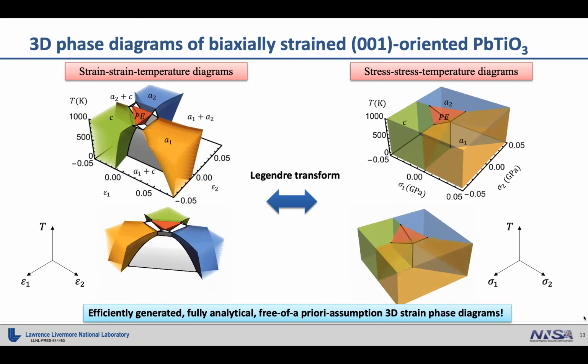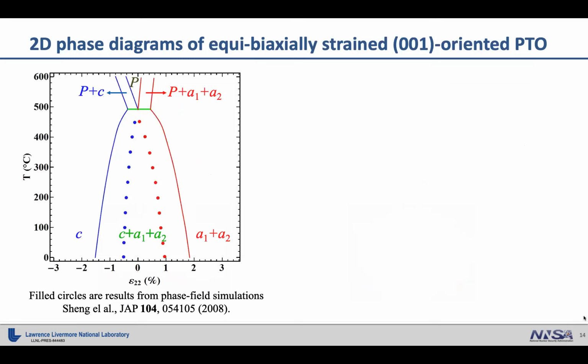And we further take a 2D section across the diagonal line, which gives us the equal biaxial strained phase diagram, which is already calculated by other methods. And we compared with the phase field simulations. We found two interesting points. First, at high temperature, there's a coexistence between the paraelectric and ferroelectric phases, which was not predicted by any